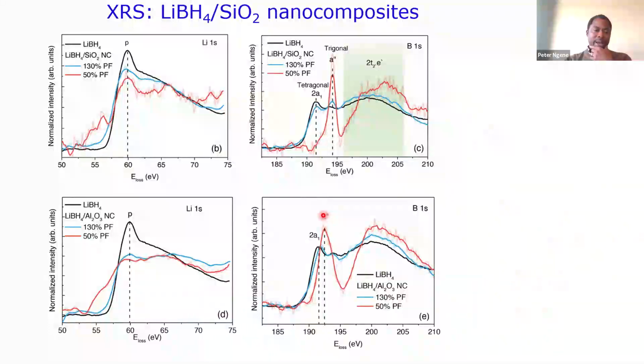So what do I want to show here? We saw that the behavior of this nanocomposite also depends on the type of oxide and the scaffold that we use. And if you focus on the boron, because the boron is much better, if we just compare this, we do see that the peak shift is different for this lithium borohydride that is confined in alumina.